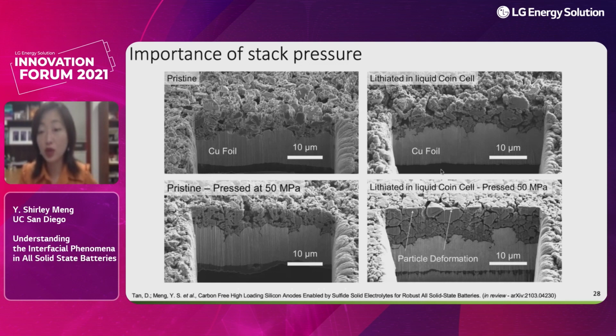My early work on the liquefied gas electrolyte was really using pressure to liquefy gaseous species under high pressure to become liquid. And we were very fascinated to see that pressure can be a very effective knob in controlling the microstructure and morphology for solid state batteries.